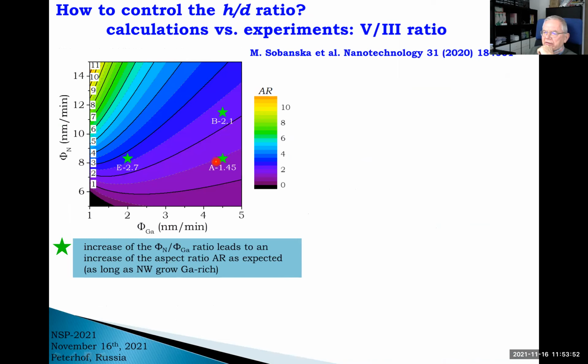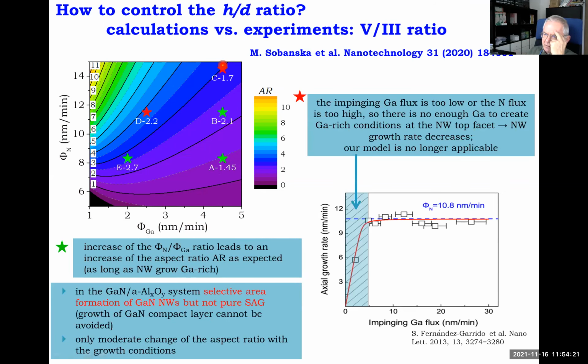Okay, we grew these three structures under these conditions, and here you see the experimental value of aspect ratio we measured on the substrate on the structures, and this looks very nice. This should be 2.1, and this a little bit more than 2. This is fine. Yeah. So under this condition, our model works. However, if we go too far, this is wrong, because we lose agreement. Measured aspect ratio is 1.7, while we expect something like 3.